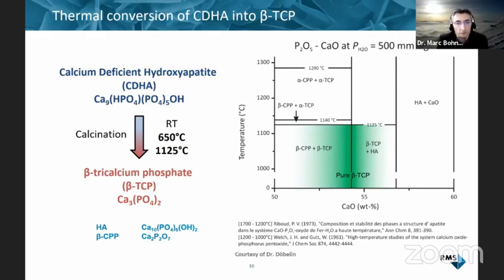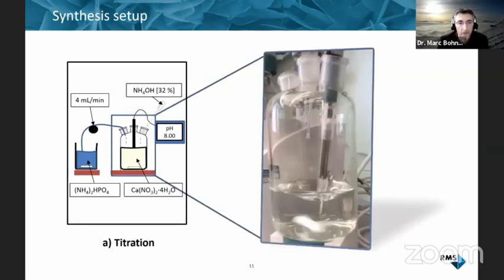We used a traditional method for this production. We started with calcium deficient hydroxyapatite that we sintered, or calcined, at 850 degrees. And we wanted to make sure that we have no chemical contaminants and that we have no secondary phases like hydroxyapatite and beta-calcium pyrophosphate. If I show here on the right-hand side the phase diagram of calcium phosphates, you can see that if you have too little calcium oxide or a bit too much phosphorus pentoxide in this area, you have the pyrophosphate as impurity. And if you have a bit of excess of calcium oxide, you form hydroxyapatite. So the synthesis was fairly standard.